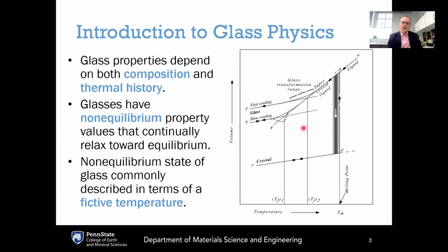We can think about that fictive temperature as being approximately where the supercooled liquid structure is frozen into the glassy state. So if it's a fast-cooled system, that happens at a higher fictive temperature. If it's a slow-cooled system, we can do the same thing here. Take a line tangent to the glassy line, see where that intersects the supercooled liquid, and then drop it down to the temperature axis. And that fictive temperature is labeled as TF1.